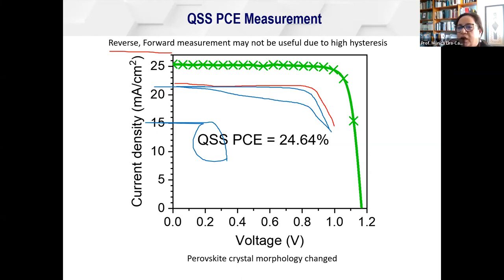We didn't have any degradation in 1000 hours at room temperature. And we observed that it was because the phosphate interaction was so strong that it immobilized ions, and we observed passivation of shallow defects. It's interesting to observe this strong interaction. But my question is, if we need phosphates to avoid the elimination of lead, and encapsulation, won't it affect, for example, the voltage and the efficiency of the solar cells? Have you done something about this?